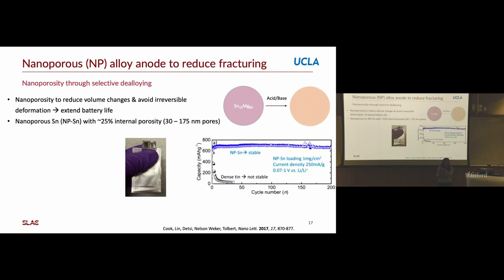Nanoporosity is actually really easy to make in these types of materials because you can de-alloy something. So here we started with tin magnesium and we etched out the magnesium. And so that allowed us to have pores on the 30 to almost 200 nanometer scale. So that's a very scalable technique. And you can see here, there's a capacity plot versus cycle number up to 200 cycles. The nanoporous tin cycles very, very well. No capacity loss really after 200 cycles, whereas the dense tin doesn't get you past 10 cycles.